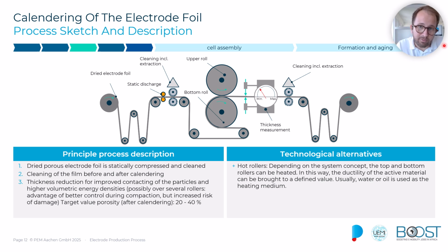So you want to assure a certain porosity, making sure the electrolyte can fit into the slurry here, but also you want to make sure that the slurry is on the right height. So that's exactly precisely the height you're targeting for your geometries mechanically, making sure it fits in the cell if you add several layers of that anode cathode separator sandwich, as we called it in the beginning, on top of each other. The cleanliness of the rollers and the process is very crucial, because you can imagine if you now press a particle with the line pressure, it has a huge impact, and you want to avoid any particles, any contamination within the process. So technical cleanliness here is crucial for a successful process.